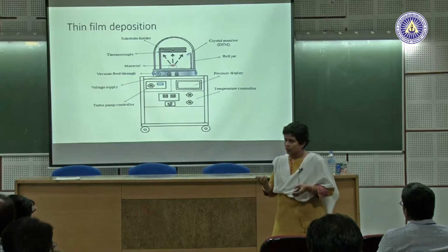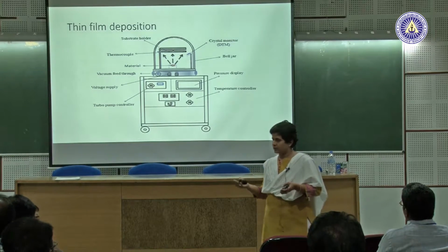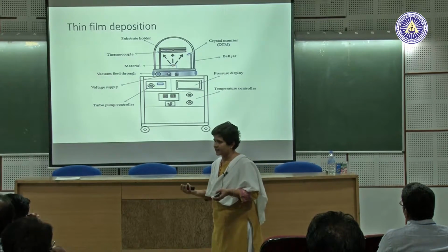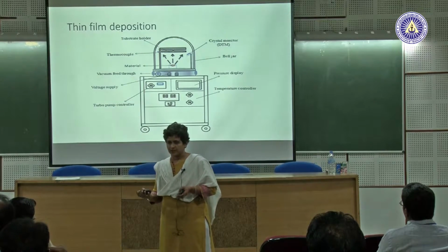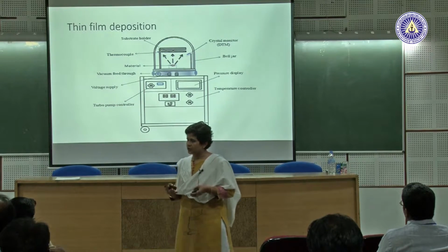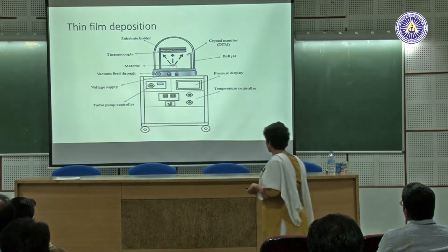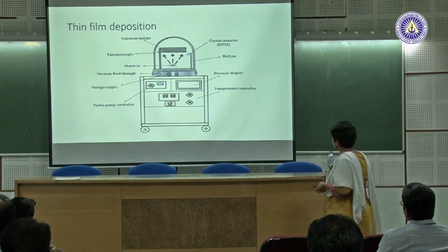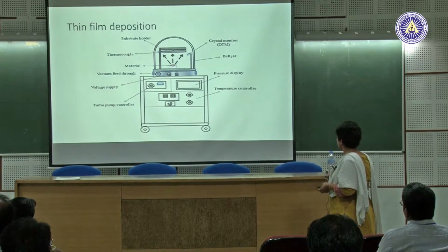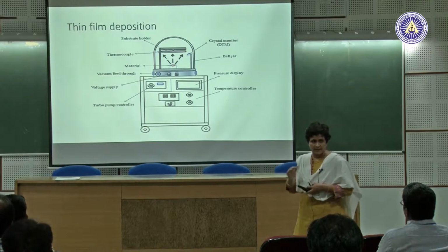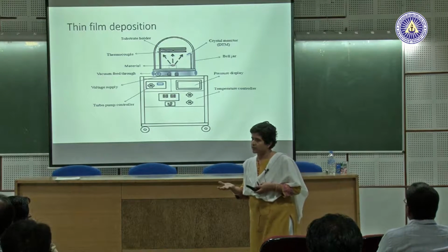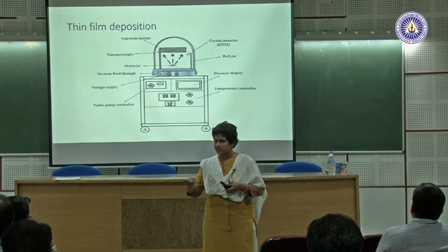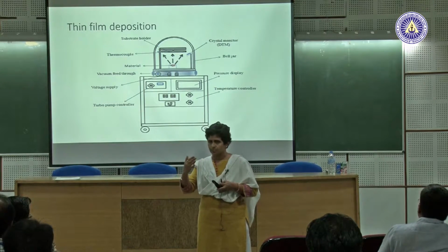Okay. So, if you want to deposit, let us say, pure aluminum, and you just evaporated it in the air, it would immediately form aluminum oxide. So, you need to keep the purity of the material you are evaporating. That is the reason for evaporation in vacuum. For electronic applications also, the surface needs to be very clean. If you do not do it in vacuum, then the surface gets contaminated and you do not get a nice binding, right.